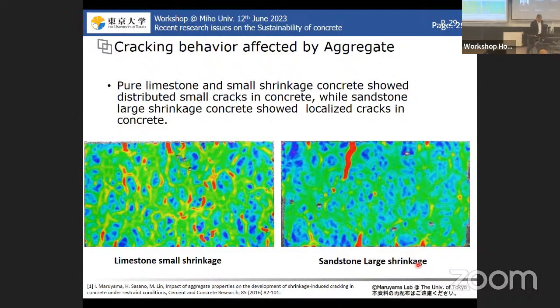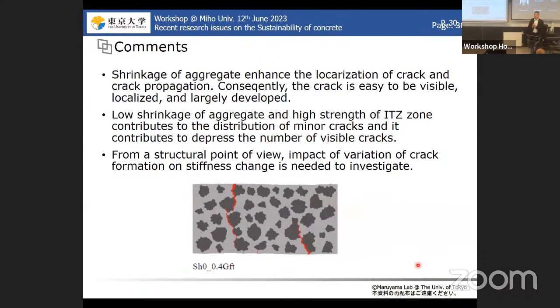So actually, the aggregate and also the ITZ properties are very important for shrinkage-induced cracking. I don't show the details about which cracking is better, but with regard to durability, it seems that the large, localized, visible crack is not appropriate, and the distributed crack is much better with regard to the permeation or diffusion of undesired elements from the outside.